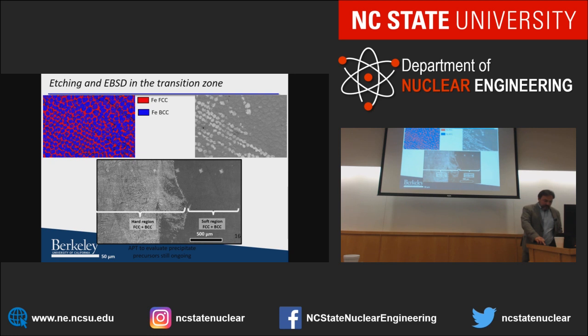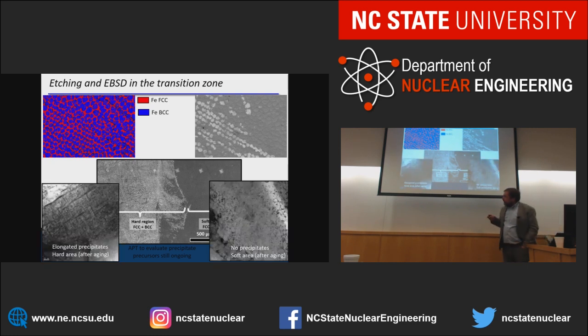So we do transmission electron microscopy, and it turns out that in the hard region, we find a lot of these intermetallic precipitates, which make our material very hard and strong. Now, in the 316 side, that doesn't seem to be the case. We barely see anything like that. And so it seems there's one precise composition layer at which you flip over where these precipitates come out, versus in the other instance, at least in normal aging condition, they will not come out. So when you think that you have a gradient which is continuous and a gentle property transition, that's not necessarily given. You may end up with a very sharp property transition from one to another, because it takes one composition, you cross over in the phase diagram to a new phase where this becomes possible versus the other one doesn't.